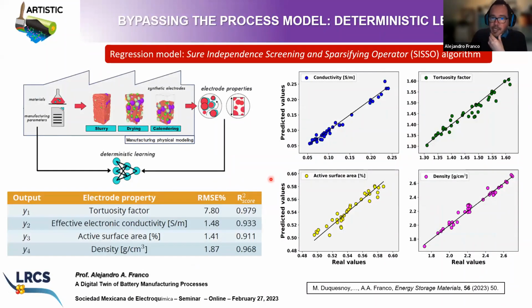In this slide, you see a little bit about the accuracy of the machine learning model able to predict electrode properties as a function of these three manufacturing parameters. And you see here the R2 scores, which refer to the accuracy, right? The closer to 1 you are, the better the model is in prediction. You see here very good accuracy in the prediction of the tortuosity factor, the electronic conductivity, the active surface area, and the density of these virtual electrodes in comparison to what you would predict by using the more computationally costly physics-based model.